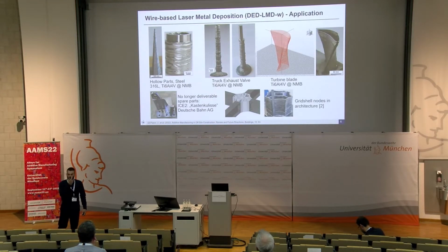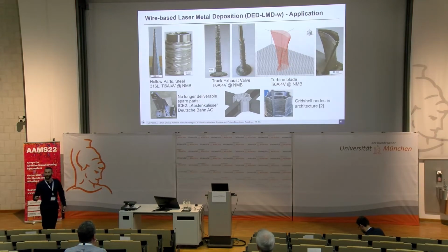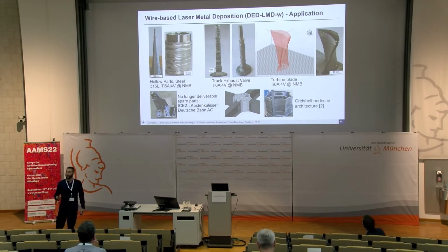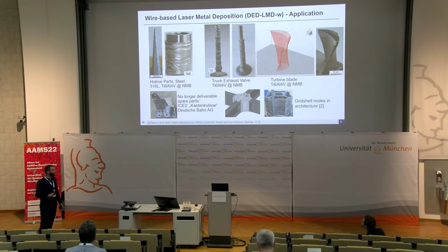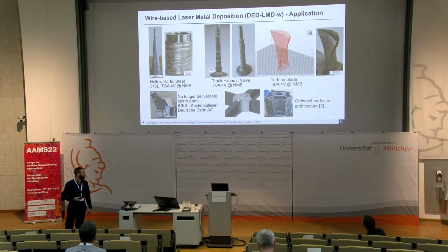So what applications do we have? First I need to mention we can compare to maybe SLM, because we can do complex parts. That's to say in the first range. But what can we do with this process? Here we see some examples we printed at Neue Materialien Bayreuth, for example a turbine blade. And what it's also good for is no longer deliverable parts. Here we see from Deutsche Bahn a part that couldn't be manufactured anymore with the old mold, so we can do it with the DED process. And also in architecture it's used for grid shell nodes. Architecture is getting more and more complex, so to combine these architectural parts we need some grid shell nodes, and that can also be processed by the DED process.